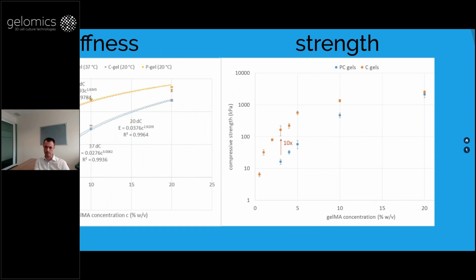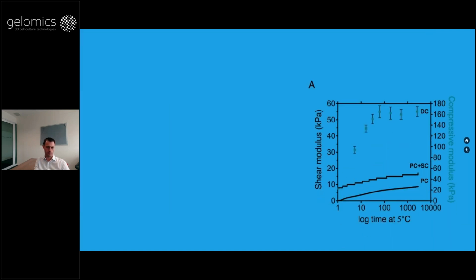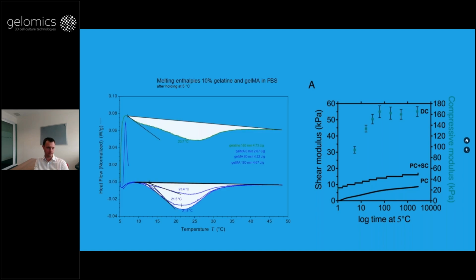Even strength is increased as well, about 10 times. And we did some DSC to confirm that we actually have this triple helix formation going on. We see a similar enthalpy, so similar energy released by letting GelMA gel compared to gelatin.